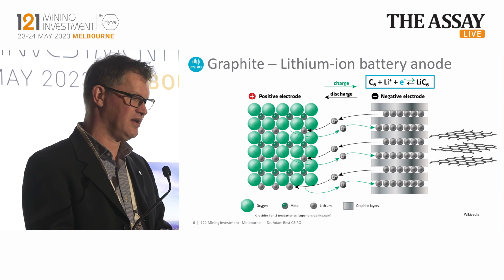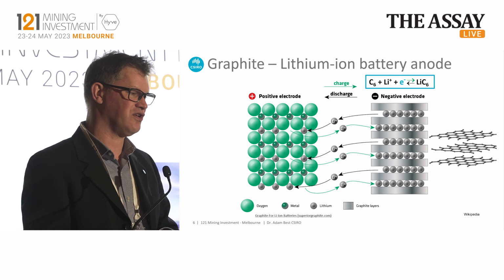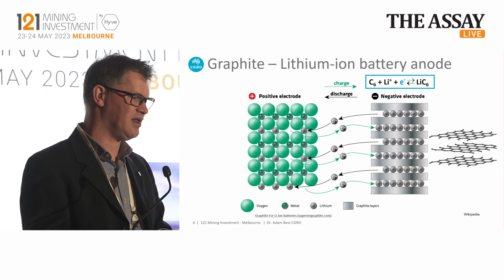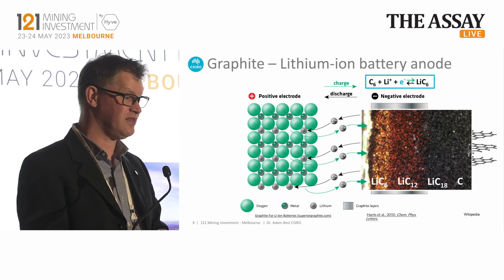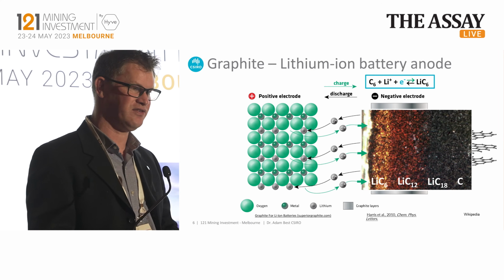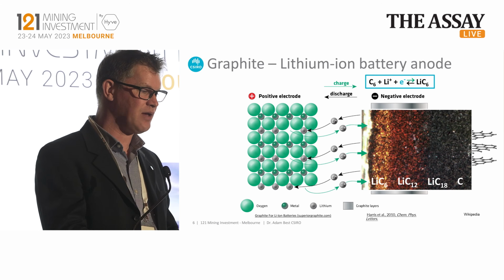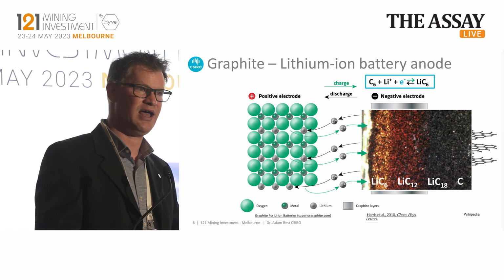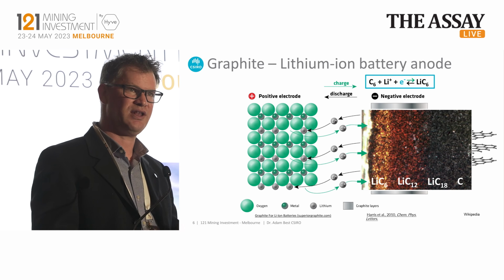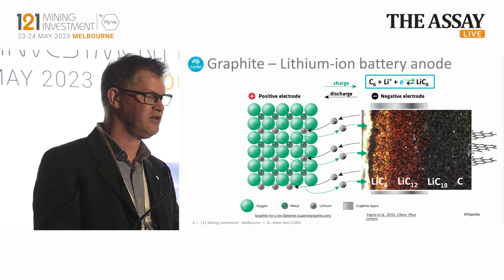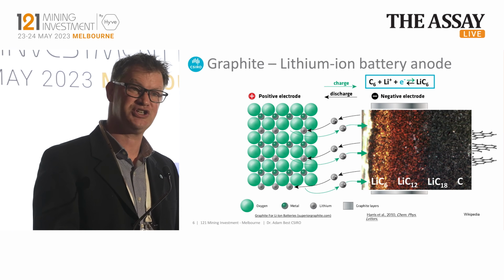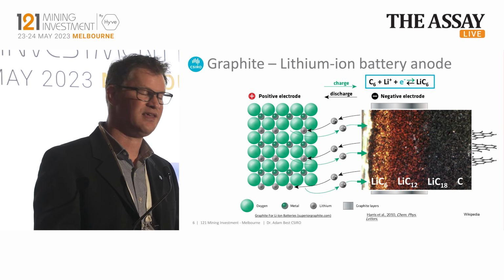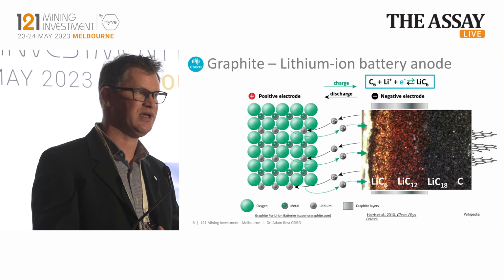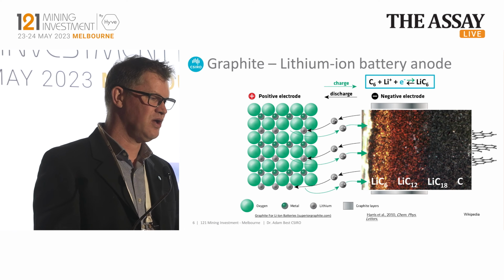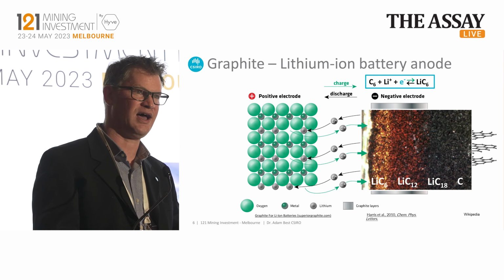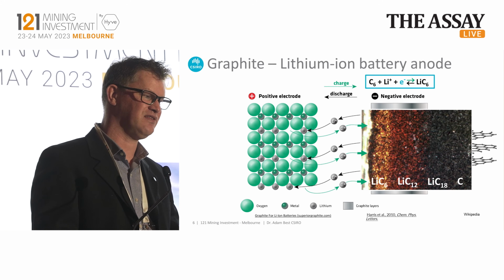So as I mentioned, there's the graphite, and this is the reaction chemistry that we use. So for every 6 carbon atoms, we have 1 lithium. This is what we actually see inside a cell. For those of you who are really interested in this, you start with a very black material, carbon, at the start of lithiation. As we go through the number of different lithiation steps in that anode, you'll actually see the color of the material change, such that when you get to the fully lithiated compound, the LiC6, when we actually take the anode out of a cell, we see it has this very beautiful gold color, which is related to the lithium that's inside the cell.